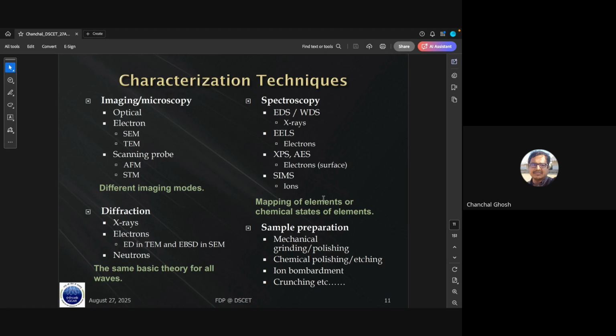If you look at the diffraction techniques, then we have X-ray diffraction. We also have electron diffraction, which will be electron diffraction in the TEM and electron backscatter diffraction in the SEM. You can go for the neutron, then also comes neutron diffraction. Probably neutron diffraction is very limited in the country. Only in the Bhabha Atomic Research Center do we have neutrons, simply because you need a neutron source, you need a nuclear reactor for that. In most modern days, they are now using a pelletron, but more or less you need a nuclear reactor for that part.